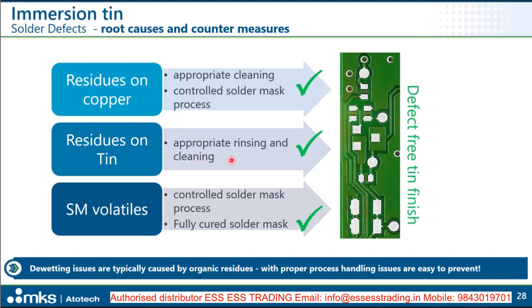It can be caused by residues on the tin, meaning the rinsing after the tin is not proper, so it's important to have a proper rinsing after the tin process to get rid of all the tin plating chemistry on the pads and the panels. And it can finally also be volatiles from the solder mask in the reflow process, which evaporate and then recondensate. So here, it's really important to have a proper, controlled solder mask process and a fully cured solder mask. And all these measures can help to prevent soldering defects.